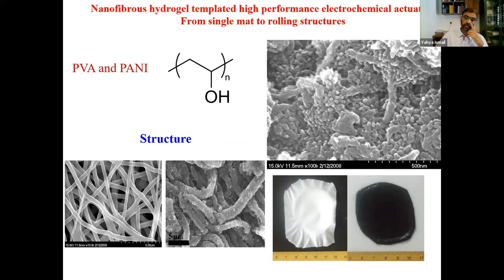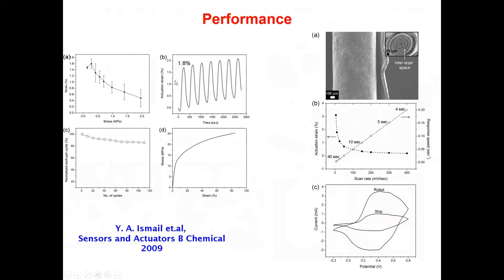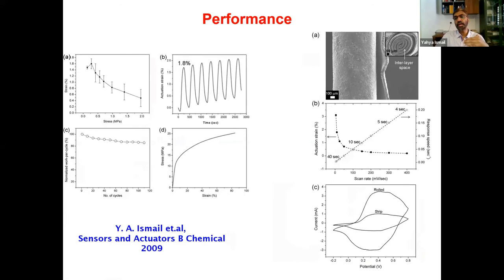And now this conducting polymer nanofibrous mat was able to produce a strain up to 1.8%. And these can be rolled up into any shape. So the real actuation strain can be, we can move even up to 4 or 5% electrochemical actuation strain in the nanofibrous mat. And we observed very good cycle stability. What we show here is only 120 cycles, but we have gone to more than 1,000 cycles. There is no dissipation of the actuation strain.